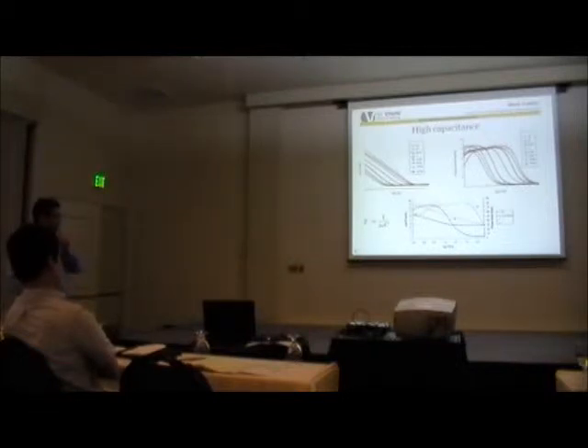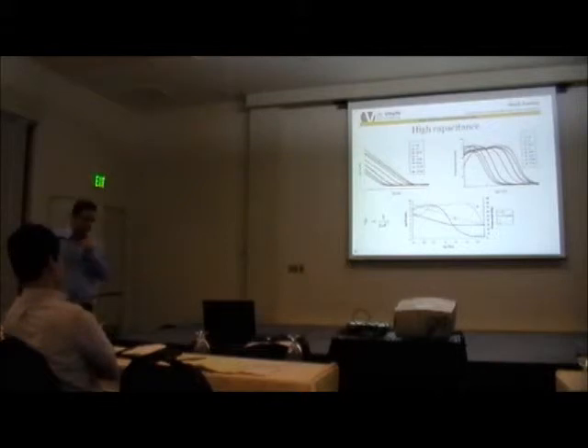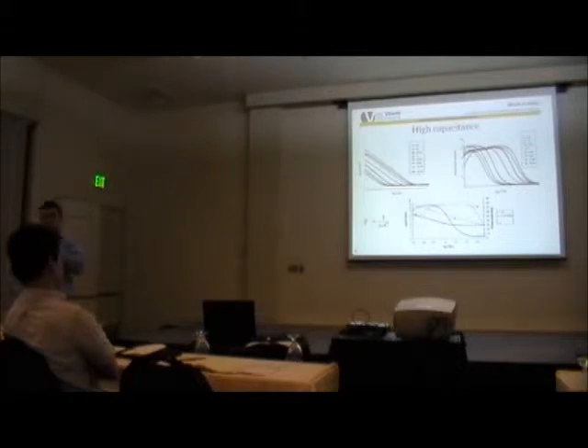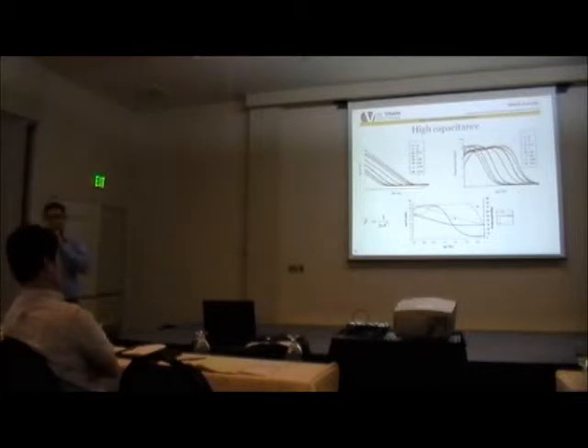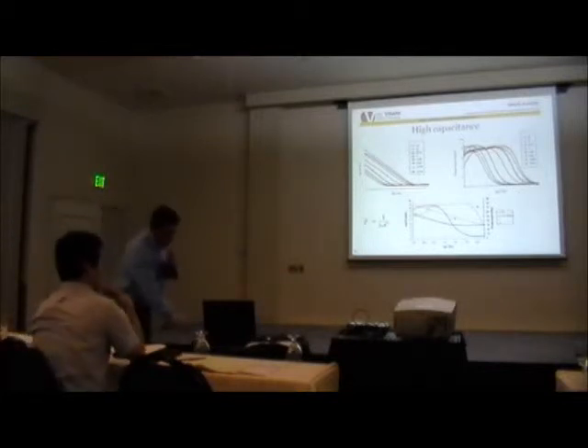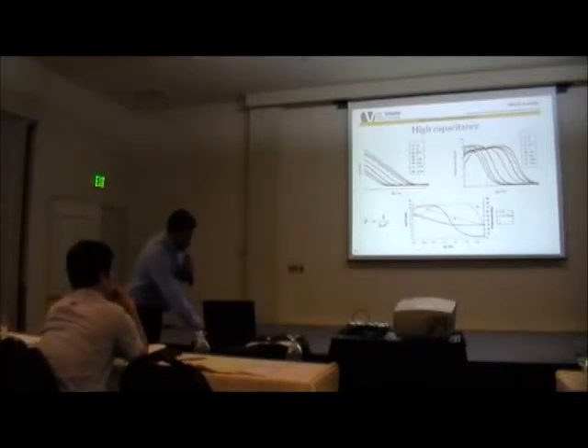These Bode plots belong to the high surface area electrode-deposited film, as I showed in previous slides, on top of a micro-electrode. The red one belongs to pure platinum, which is very smooth. After deposition, we see that more than two orders of magnitude — roughly about two and a half orders of magnitude — impedance was improved, or capacitance was increased.